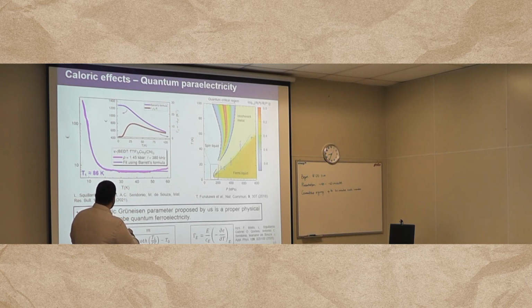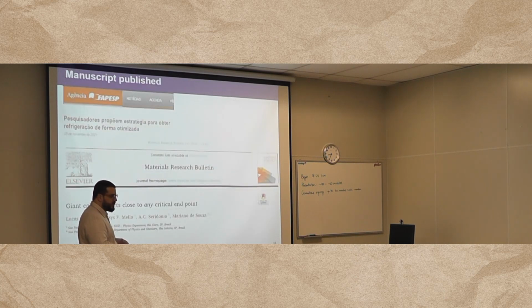And not only that, we have applied to this quasi-two-dimensional system, kappa-BDT-TTF2, the so-called spin liquid candidate in the literature, Barrett's formula, and we have seen that the temperature at which this plateau would happen is close to 88 Kelvin, which is associated with the quantum critical region. And then we were able to infer that this would be a good area of the phase diagram to perform caloric effects in the system, of course, because of the entropy accumulation as discussed. So these last results gave rise to another nice publication in Materials Research Bulletin in 2021.